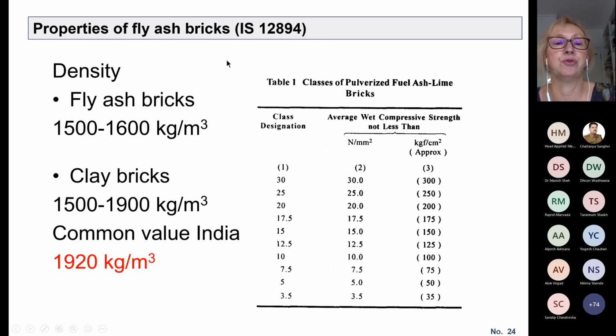Here is a summary of fly ash bricks for India, including the class. The density is 1500 to 1600 kilograms per meter cube, whereas for clay bricks it is 1500 to 1900. I usually take 1920 as the common value in India, kilograms per meter cube. Here in this table you can see the class designation. It is the same as for clay bricks: the class designation is equal to the compressive strength in megapascals. So if we say class 15, that means the compressive strength is 15 megapascals, or 15 newtons per millimeter square. That is good news: whether it's fly ash brick or clay brick, you can specify the class in the same way. We call it class, not grade. And you can see the full title is Pulverized Fuel Ash Lime Bricks, or PFAL.